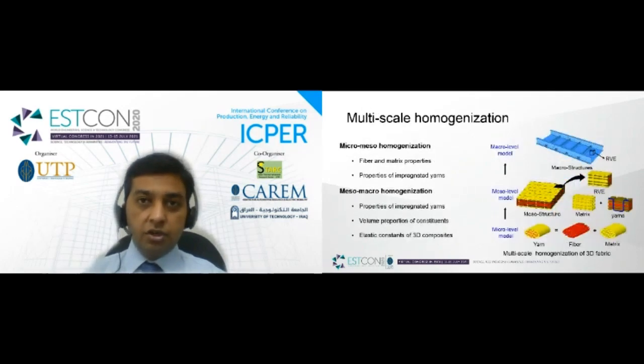Now, the multi-scale homogenization of 3D fiber reinforced composites. The elastic constants of 3D composites depend on the elastic constants of constituents and their arrangement in the 3D fabric architecture. These elastic constants can be determined analytically or through finite element analysis using multi-scale homogenization. The multi-scale homogenization is further divided into micro to meso homogenization and meso to macro homogenization. In the case of micro to meso homogenization, we determine the elastic constants of impregnated yarns from fiber and matrix properties, whereas in the case of meso to macro homogenization, the elastic constants of 3D composites are determined using the elastic constants of impregnated yarns and their volume proportions in the representative volume element.